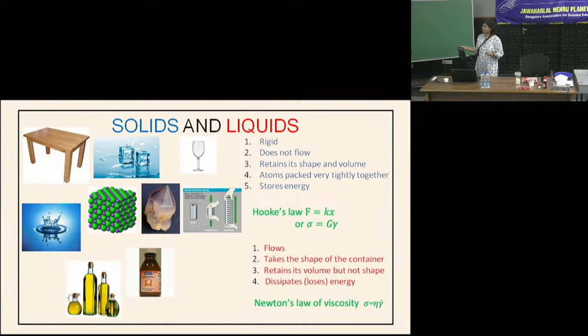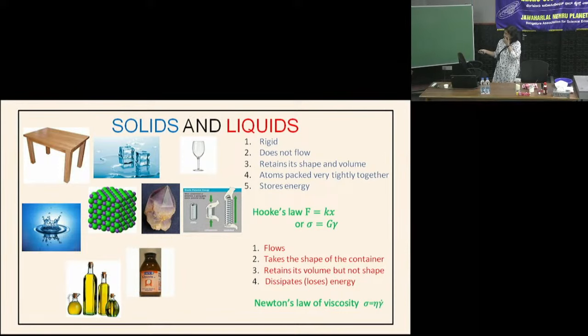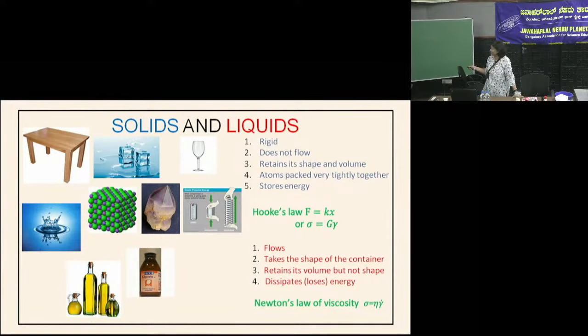And liquids are described by the Stokes-Newton's law of viscosity, which says that, unlike Hooke's law, where the stress is proportional to the strain, Newton's law of viscosity says that the stress is proportional to the rate at which you are applying the strain. The proportionality constant is eta, the coefficient of viscosity, which tells you the resistance of the material to flow. The higher the viscosity, the higher the eta, the less the material wants to flow. Technically you can think of a solid as a material with infinite viscosity.